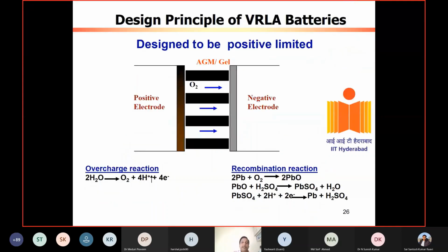So the main advantage is that the oxygen which evolved at the positive electrode will go through the pores of this and combine at the negative electrode. So what will happen? Pb reacts with the oxygen to form PbO at the negative electrode, and with sulfuric acid you can have a kind of cell discharge reaction. But this is a discharge product. As the cell is under discharge, lead sulfate formation is a disadvantage, but as the cell is under charge, lead sulfate gets converted to lead.